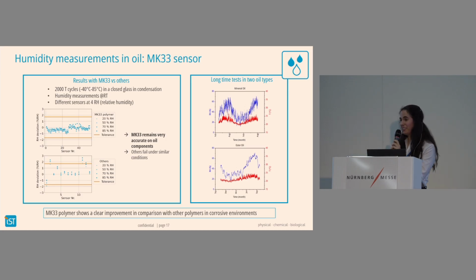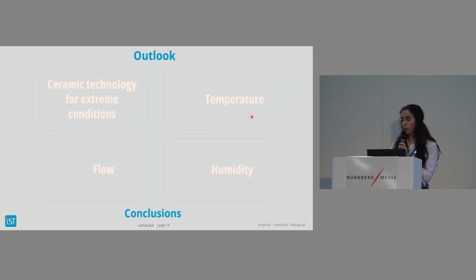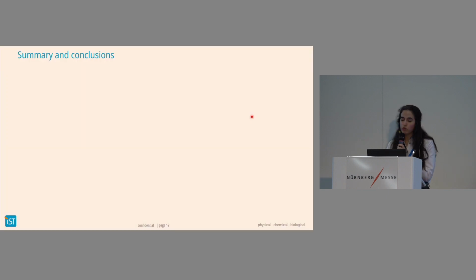This change is basically due to the change of temperature or to the oil itself that can react better or worse to humidity. So exactly, this would be a bit the conclusion of this slide. The MK33 is the most robust polymer that we have developed for rough conditions. So with this, we can move to the conclusions.